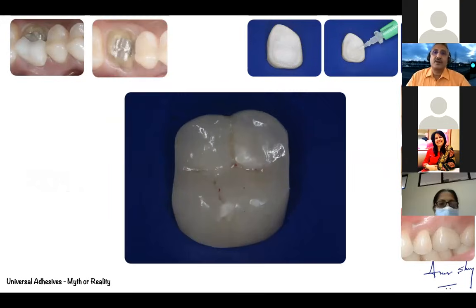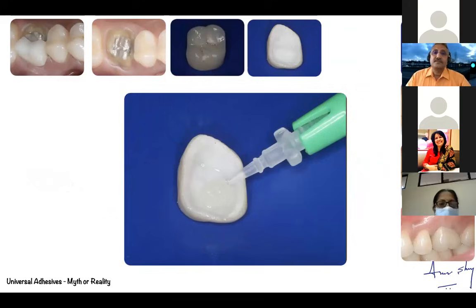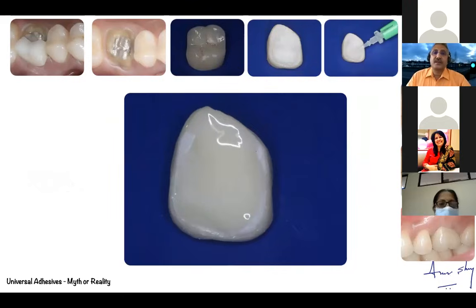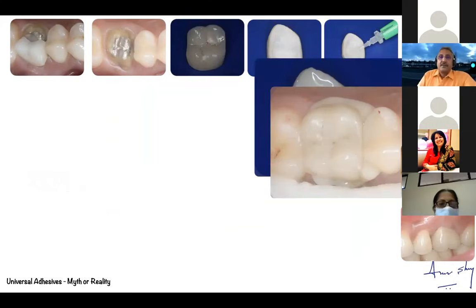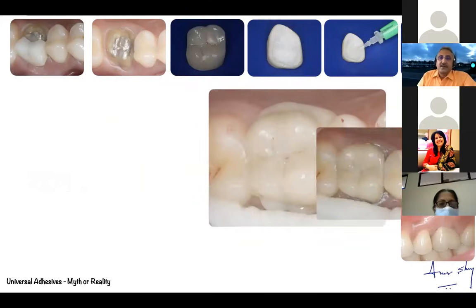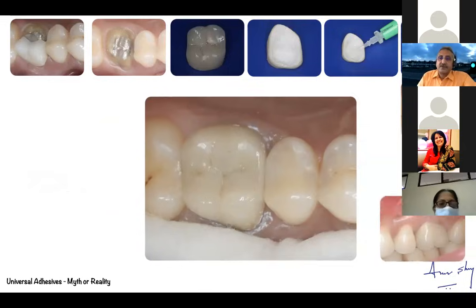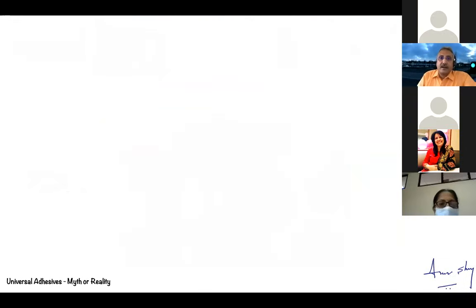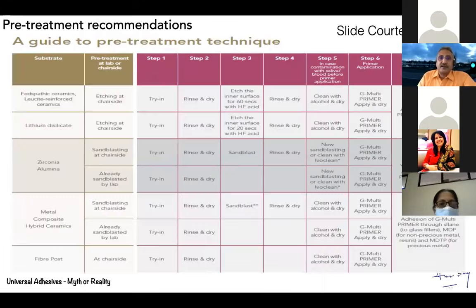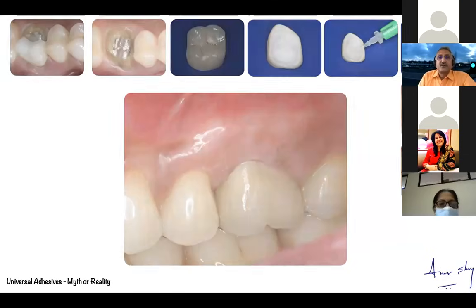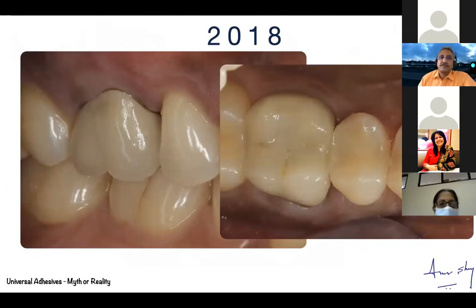So this is a bonded crown. This was not done with a universal adhesive. This was done with an older adhesive, and it was done with a metal primer, that is MDP finally, but not a universal adhesive, because back then universal adhesives were not available. This is the first generation of resin cements which was used, and 12 years later, it's still in function. No fractures, no failures, because attention was paid to exactly how we cemented or bonded it.